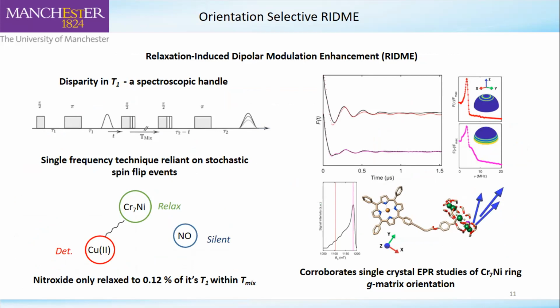So we can do relaxation-induced dipolar modulation enhancement experiments, which is this somewhat scary looking pulse sequence, but it just breaks down to a Hahn echo detection sequence followed by this T mixing block, which basically replaces your pump pulse in a DEER experiment. It allows your faster relaxing spins to relax, and then that's refocused. So it's a single frequency technique that relies on a fast relaxing spin to relax, modulating your detection spin echo.